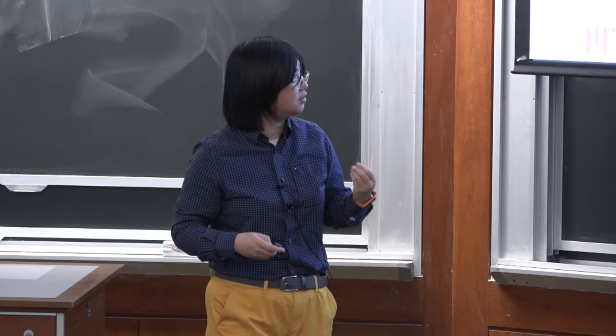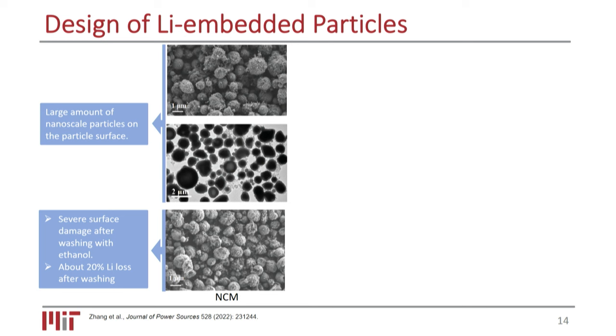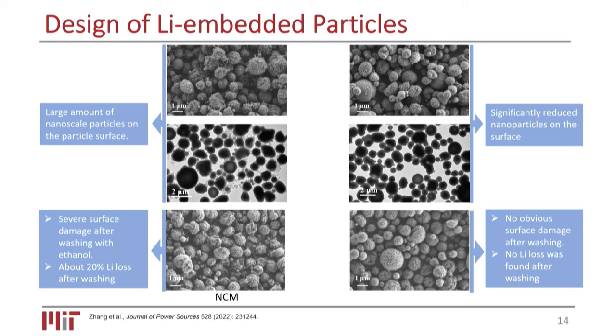So after identifying this issue, it's the same issue, just with a different TEM and SEM to further summarize the problem. And this is the magic we did: you could clearly see the difference, that we don't have these nanoparticles anymore, and we have a pretty nice distribution of the particles. And here is the story. I want to unbox this and share with you: by adding 2.5% of urea into the precursor, we magically remove the nanoparticles that appeared at the surface. And they can already have a uniform distribution inside the particle. And I'm going to explain to you why and how we can do this.